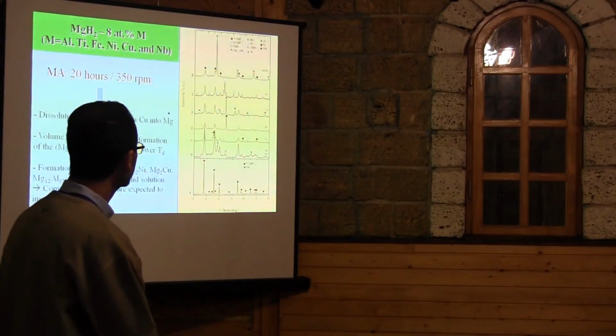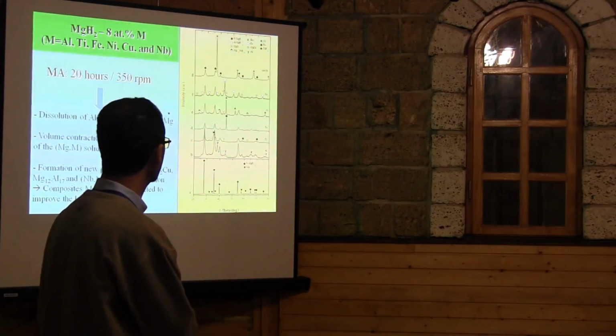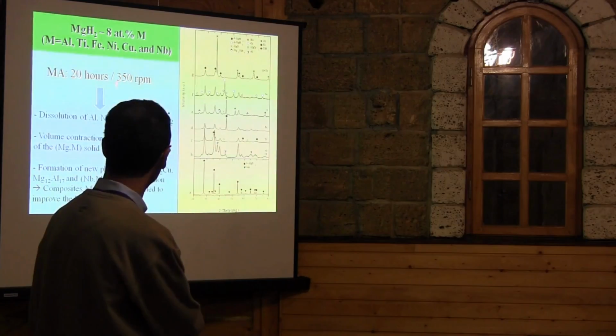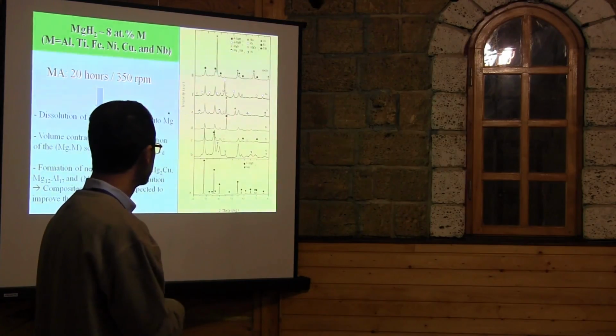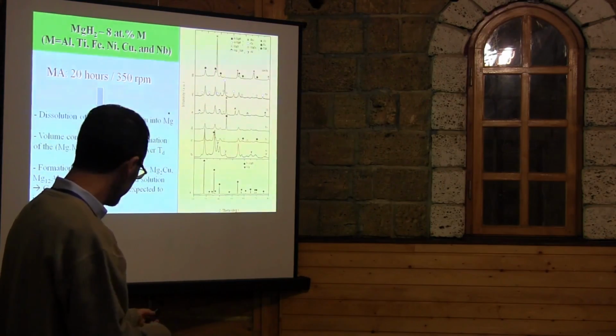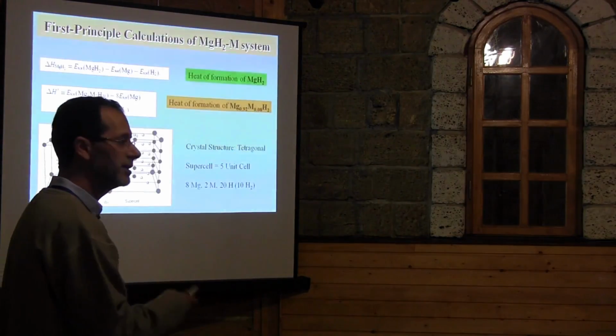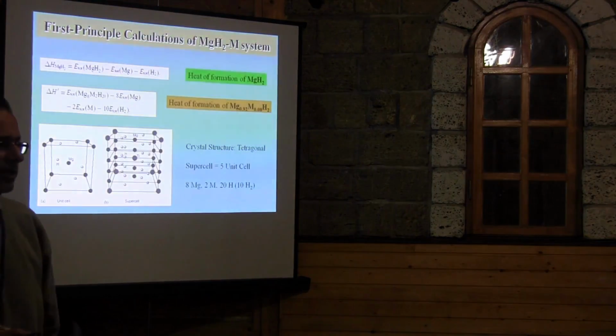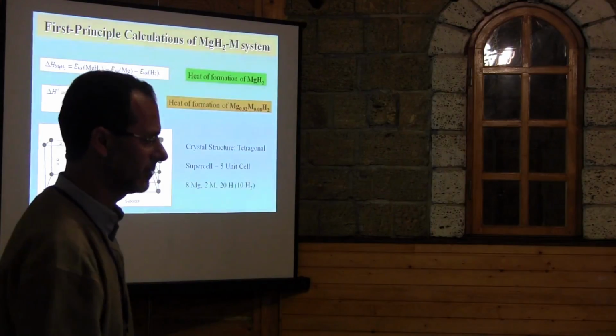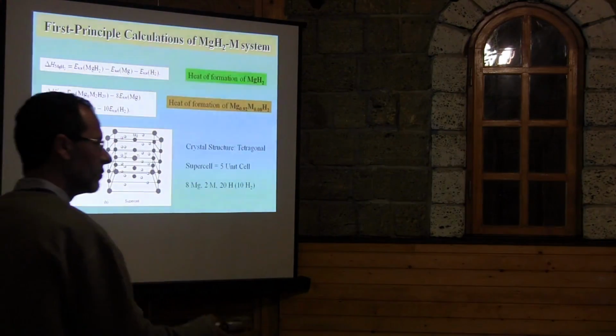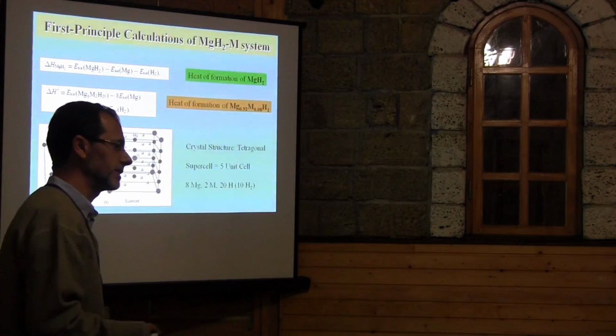So now we did magnesium hydride. We tried to mix with transition metal. So we choose this kind of element. Before I prepared this system, we did DFT calculation, density functional theory calculation, again to predict which element will give me the best properties.